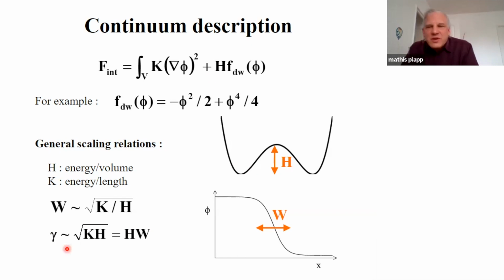Okay, so you get very simple scaling relations that are universally valid between the two coefficients that appear in this functional and the surface energy and the interface width. That means in the top-down approach, if you know the surface energy because somebody has measured it, and if you have an idea either what the physical interface thickness is or what interface thickness you would like to produce to solve a mathematical problem, then you know how you have to choose these coefficients K and H.